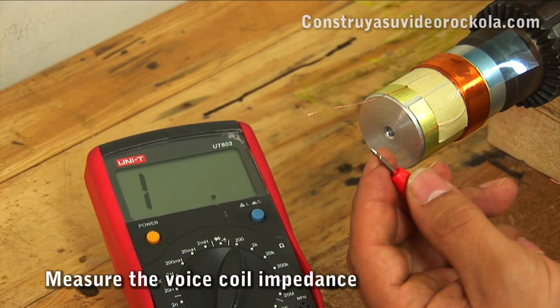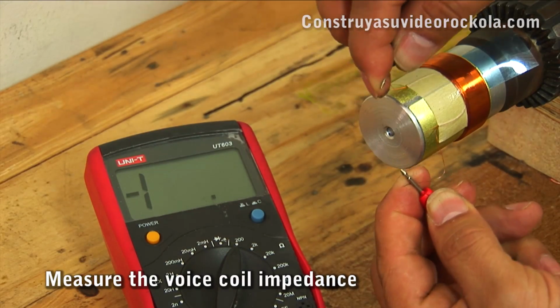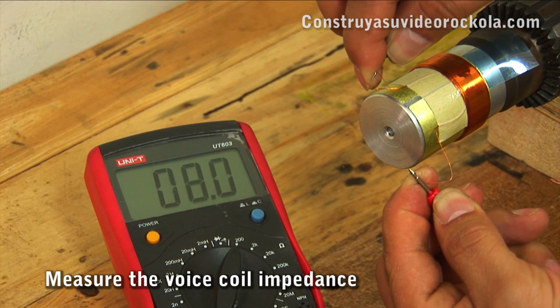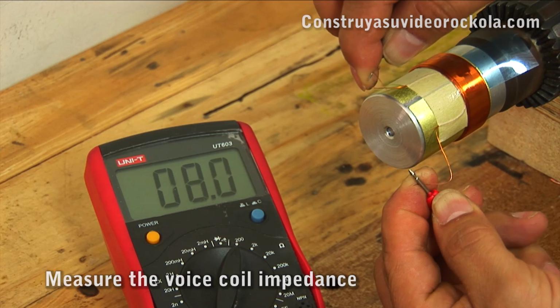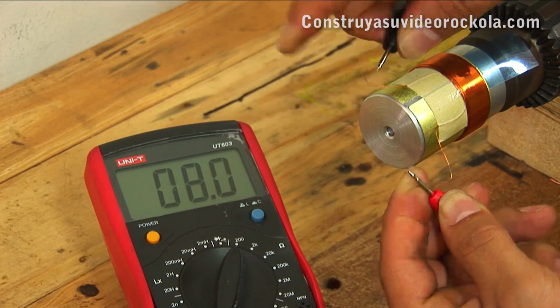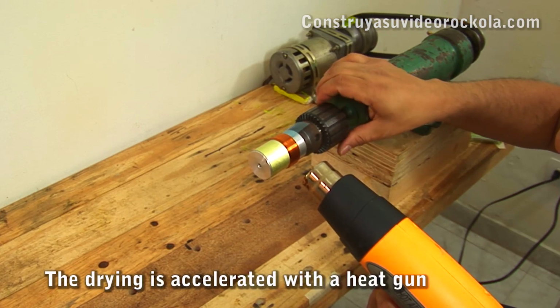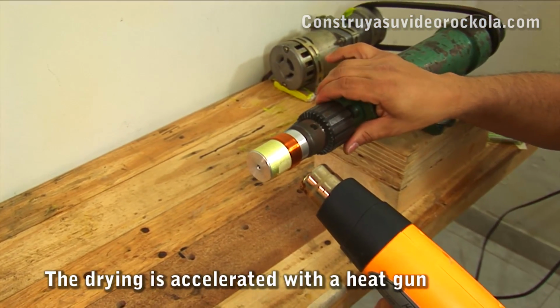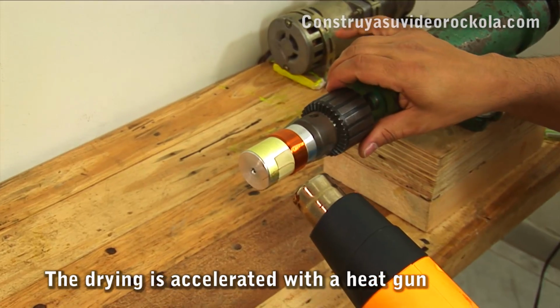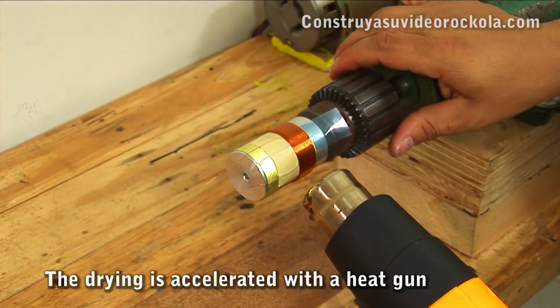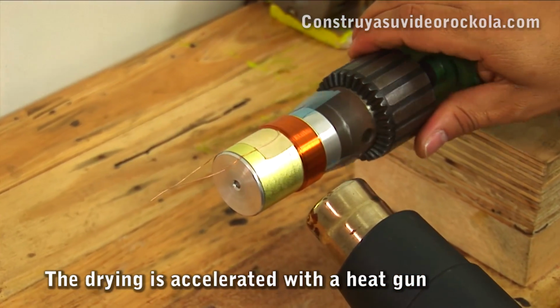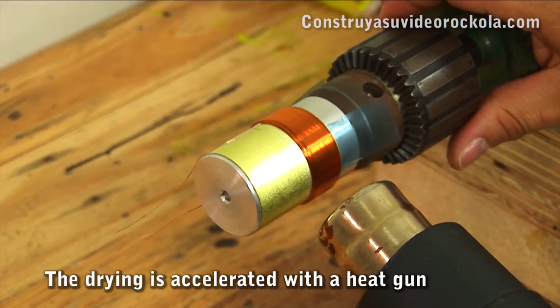We measure the voice coil with a multimeter on the scale of 200 ohms, and we check that we have the correct impedance. Because the epoxy resin is slow drying, up to 24 hours, we can accelerate the process using a heat gun. In addition, the high temperature helps to seal the resin for more strength.